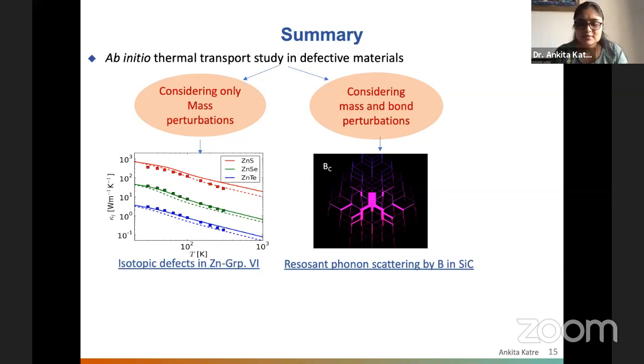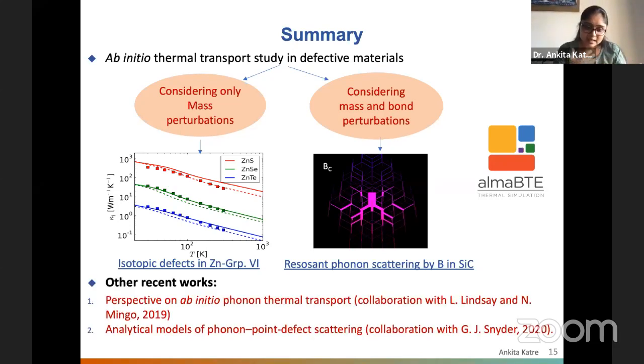And with that, when we see the results, we find very interesting results for this, as I showed you in the case of silicon carbide here, and the boron defect in that case. So this has been implemented in almaBTE to calculate the thermal conductivity, and we are working with that code here.